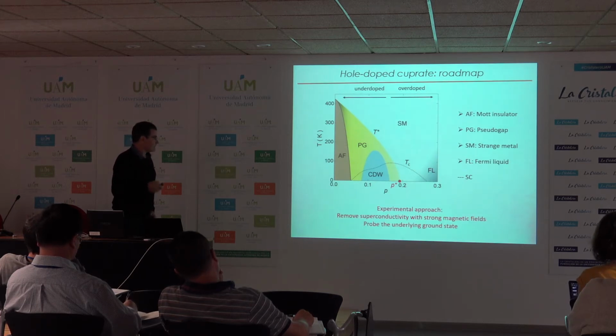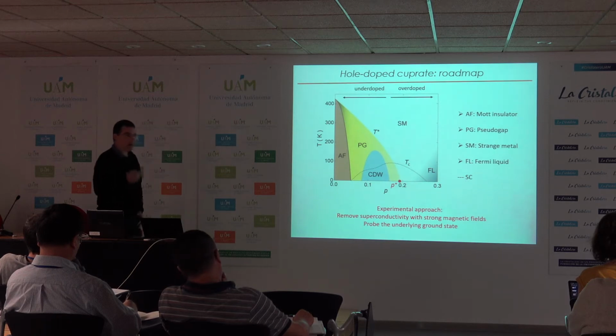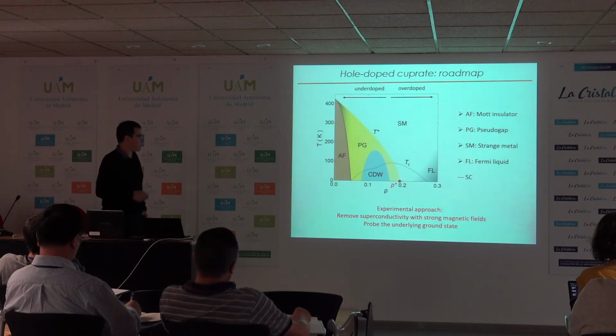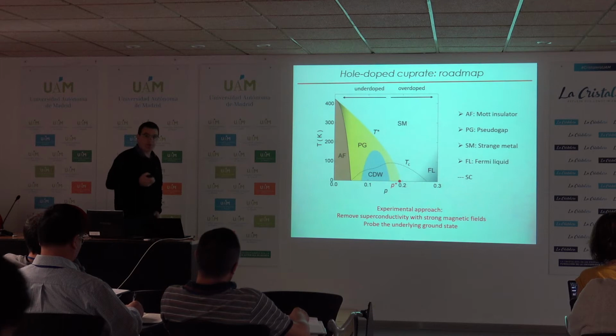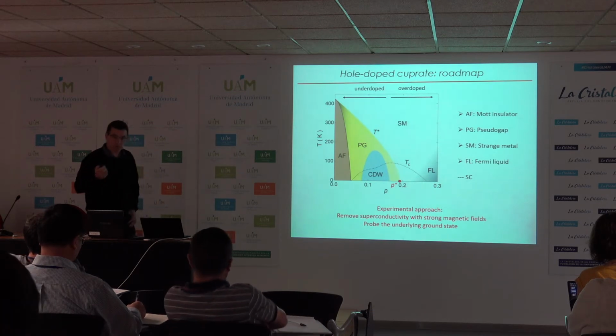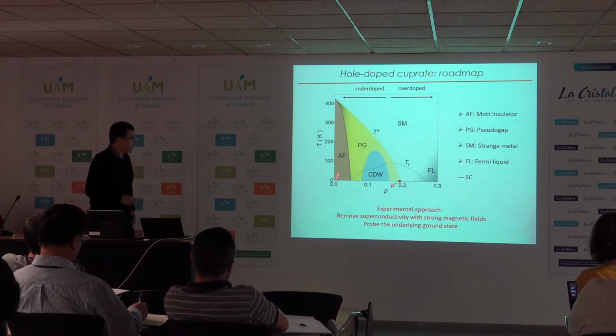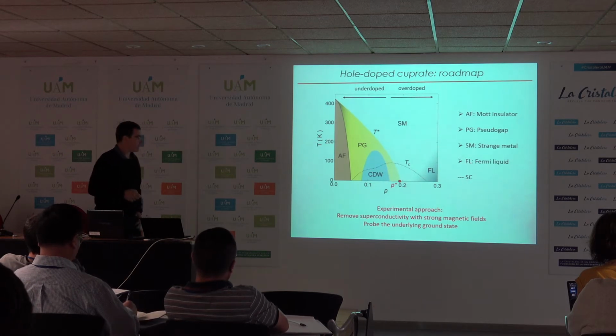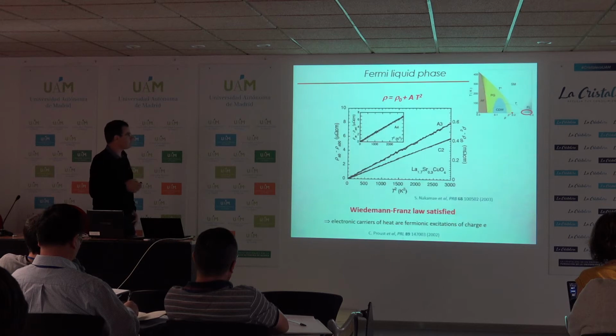And this is our approach. Remove superconductivity with a strong magnetic field where we can do it, because in YBCO around optimal doping, the critical field is believed to be 150 Tesla, so we cannot reach low temperature, but we can study the phase on both sides of this critical point.